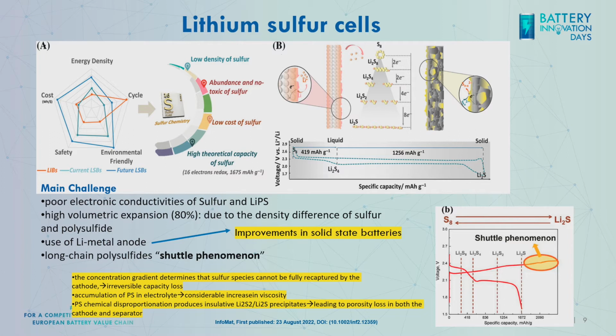So the discharge curve is reported here. You have 2 different steps. The first step is for the long chain polysulfide ions that are forming, and the other one for the shorter chain. These intermediates with different chain lengths are anions, and for this reason they are soluble in the electrolyte. So, of course, we can have this so-called shuttle phenomenon.